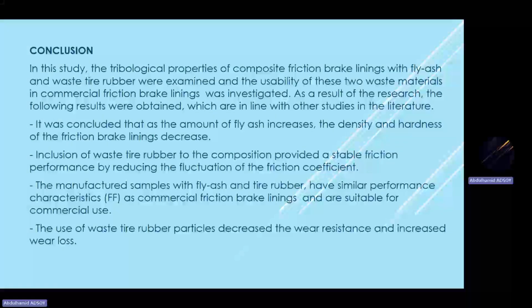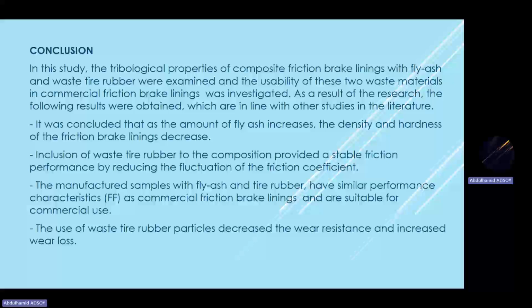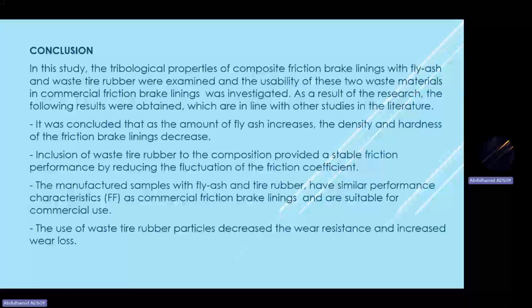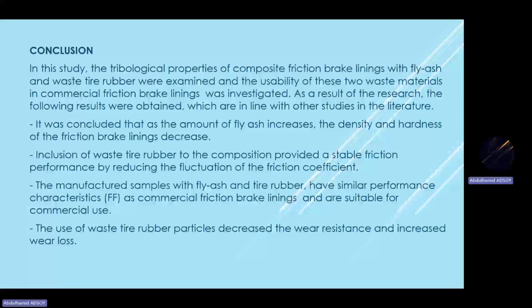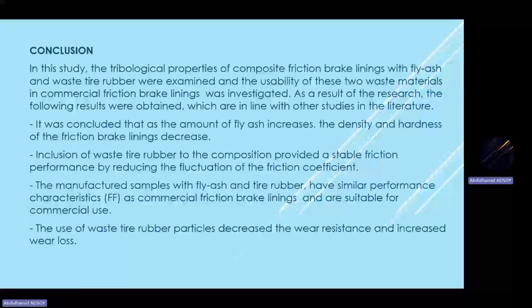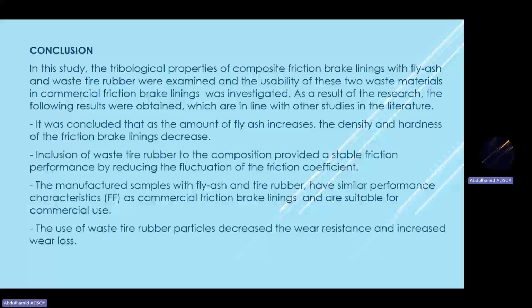Inclusion of waste tire rubber particles in the composition provides a stable friction performance by reducing the fluctuation of the friction coefficient. The manufactured samples with fly ash and tire rubber have similar performance characteristics, meaning FF grade markings, as commercial friction brake linings and are suitable for commercial use. And the use of waste tire rubber particles decreased the wear resistance and increased the wear loss.